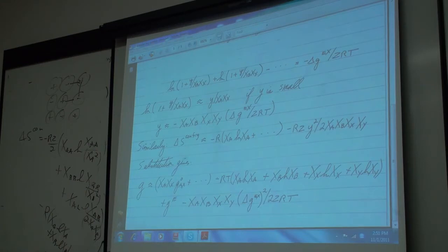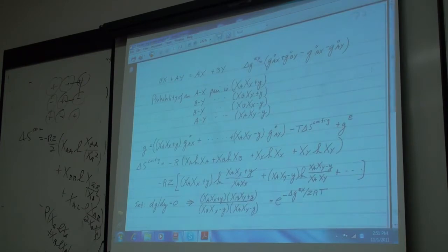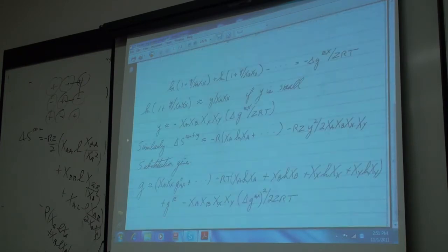So you might want to do this mathematics yourself. It doesn't really matter. This was on slide 22. Play with the math, but it's right. After all that, it ends up being a very simple polynomial term here, the product of all 4 site fractions. So that's going to have its greatest value in the center of that composition square. And it's always negative.